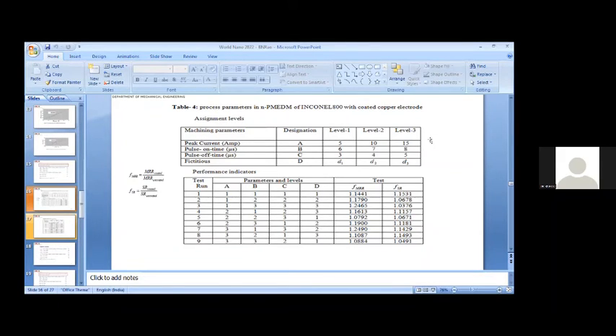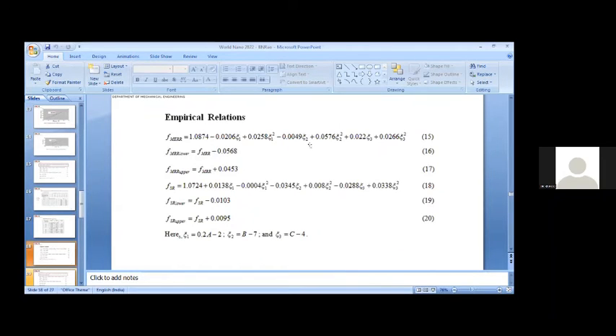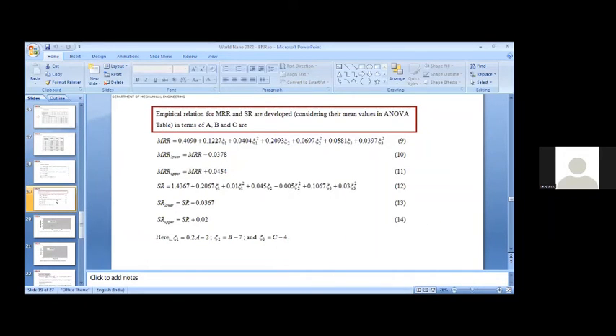So here the base I am assuming is without coating, uncoated, and coated copper electrodes I have taken. The factors I have arrived at are MRR coated by MRR uncoated, and surface roughness coated by surface roughness uncoated, so that once these factors are available from the previous experiment itself, with these factors we can find out what could be the range impact of coated copper electrodes on the performance indicators. So we are able to find out the empirical relation similarly to what we have done earlier. And from that empirical relation and the previously uncoated one, we have developed the empirical relations for the coated one.